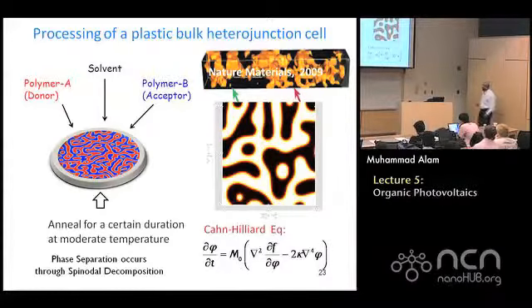So this is not really two polymers. It's two polymers, but, not for PV, one has a very high number of protons. The nucleus is very high, so that when you do electron tomography, you can get the Z contrast out of it. So that is how this picture was taken. Electron tomography is very popular; anytime you want to do a three-dimensional complicated structure, I see it used all the time. So this is how the picture was taken, suggesting that this way of thinking about the material is okay.